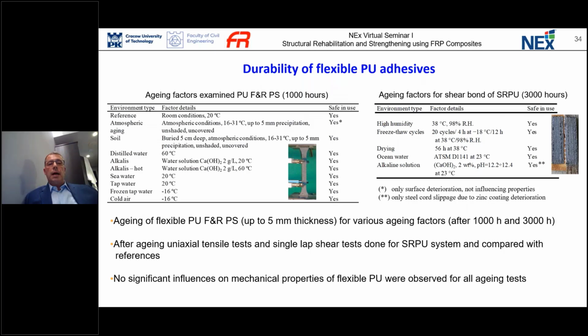Also, we did many tests according to durability of these polyurethane flexible adhesives. Please do not identify these polyurethanes with polyurethane foam that we use for installation of windows, because it is a completely different special material. As you can see here, we tested it for various aging factors after 1000 hours and also 3000 hours. In this case, no significant influences on mechanical properties of these flexible polyurethanes were observed during these aging tests.